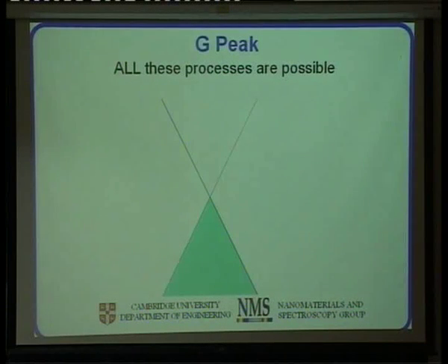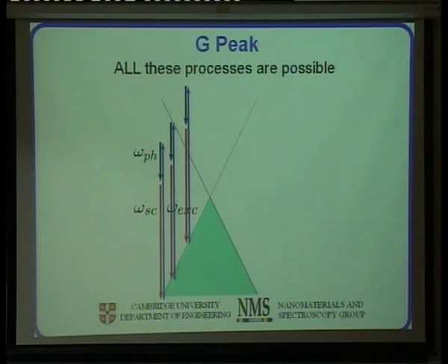So in fact, in the G peak, it's not as simple as I showed before, but all these processes, in a pictorial way, are all possible. In principle, we think, okay, this one is the most resonant one, so these two will go to 0, but that's not really the case. You need to do the sum and see exactly what goes on. But what is intuitive is that if I change the doping, for example, I can kill some of the processes, and for example, if this one and this one were canceling out for some reason that we don't really know, in this sample they will not cancel out anymore. So there is a way of tuning the weight of each of the matrix elements in the sum, and doping is the easy way to do it.